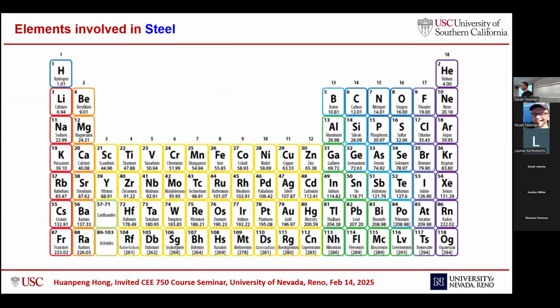And also, compared with conventional steel, this is the periodic table. As we all know, steel is made of iron, sometimes with carbon or manganese, sometimes with some chromium, nickel, or silicon. For most steels, the matrix or main elements are fixed. We know that steel is made of this composition. However, for shape memory alloy, there's no certain composition. Any material or any alloy that exhibits the superelastic effect and the shape memory effect can be categorized as shape memory alloy.